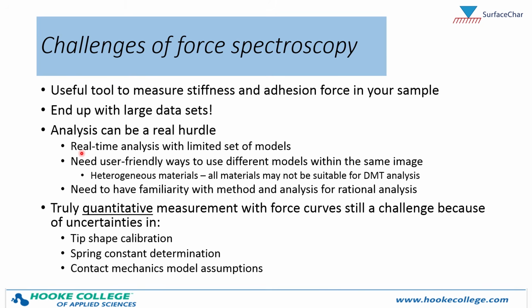Generally, the approach is that you collect the force curve data and then you go back offline and you analyze it with more sophisticated models or some tweaking in the models in terms of what portions of the force curve you want to fit. For heterogeneous materials, and we saw this on the impact copolymer sample, all the materials may not fit one model. So if you remember in that particular sample, the rubber was really more appropriate for the JKR, but the matrix material was more appropriate for the DMT model. So you need some ways, especially for heterogeneous materials, to be able to model certain components with one model and other components with a different model.